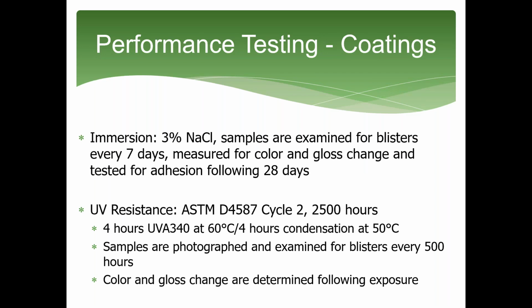For immersion testing, the samples are immersed in a 3% solution according to ASTM D6943 method A for a total of 28 days. The samples are examined for blistering every 7 days. Color and gloss change are evaluated following 28 days.